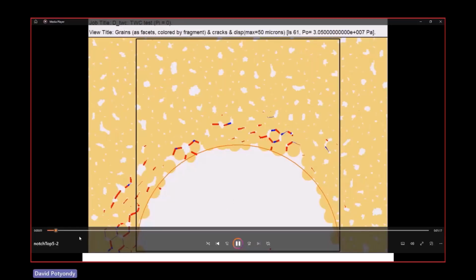Notice at this point, this was loaded to 30 megapascals on the outer boundary. And at that point, this is the damage that existed, because this thing doesn't just go from no damage to failure. It slowly progresses in damage as you increase the outside pressure. Here you're seeing the power of the flat jointing. These cracks are partially broken. These edges, these boundaries are partially broken. These are fully broken. Red is tensile breakage, blue is shear breakage.